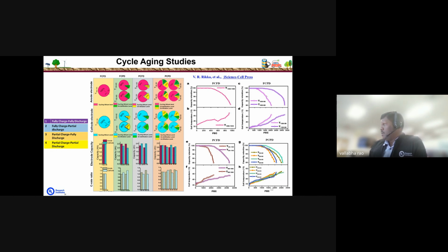In the case of full charge and partial discharge, it showed around 3600 cycles, which means almost 10 years of lifetime. And in the partial charge and full discharge, it has above 10 years of lifetime. So even though we are charging at a higher C rate, which means less than or equal to 15 minutes of charging, which is a demand for our EV applications, these test conditions significantly show the highest cycle life.